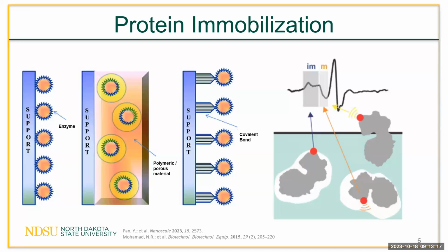In a paper recently published in my group on the right, you can see that if we use site-directed spin labeling EPR with the MTSL spin label, we can actually analyze the confinement of these proteins based off of EPR signal. If a MTSL spin label is exposed at the top of, say, a metal organic framework, and it is free to move around, we will see a mobile peak on the right there.